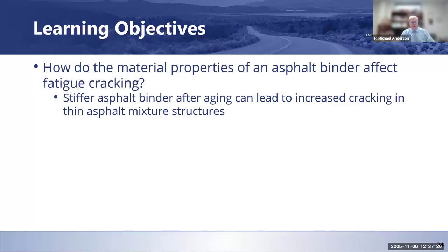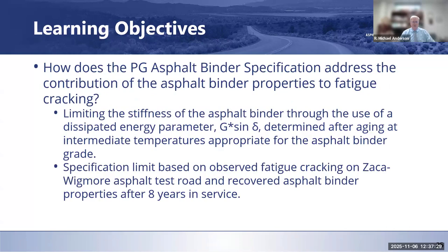How do the material properties of an asphalt binder affect fatigue cracking? Stiffer asphalt binder after aging can lead to increased cracking that we see in thinner asphalt mixtures in particular. And then the last thing we talked about in the learning objectives at the beginning was how does the PG asphalt binder specification address the contribution of the asphalt binder properties to fatigue cracking? We want to limit the stiffness of the binder through the use of the dissipated energy parameter. That was G star times sine delta.